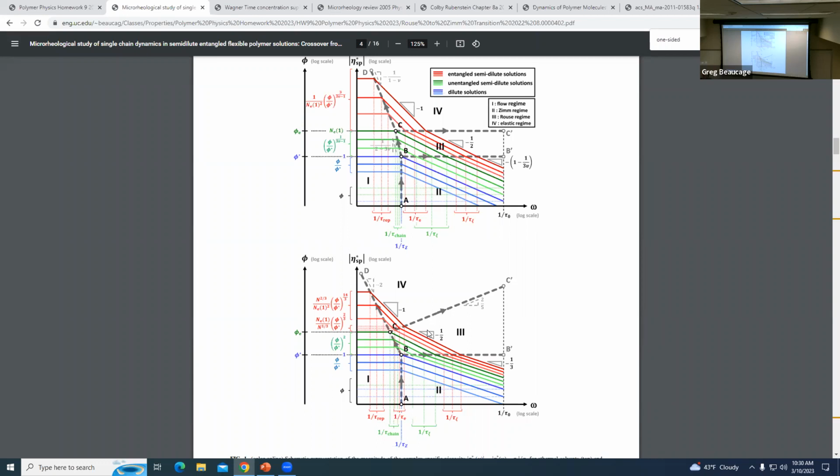And then when you get to below the Rouse behavior, the Rouse is made up of concentration blobs. In other words, the Rouse behavior is a bunch of concentration blobs moving through the tube. And then when you get to shorter times or higher frequency, you see the individual blobs, which are just like Zimm blobs moving around in a fluid. It's sketchy. It's kind of like a pretty convoluted thing. One thing adds on to another. And so anyway, that's what he wants to demonstrate, that 1/3, 1/2, 1. So he's got Zimm, Rouse, and then this is reptation.